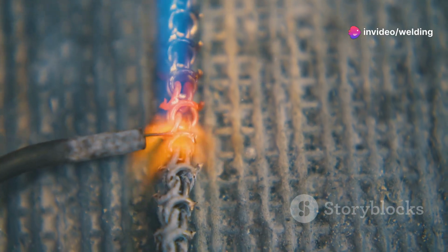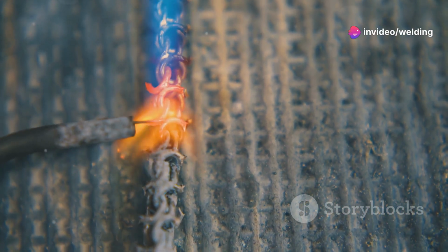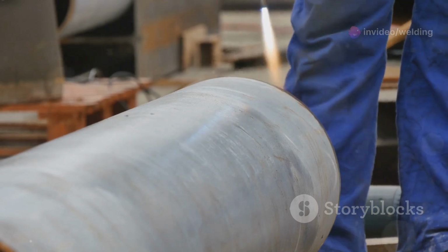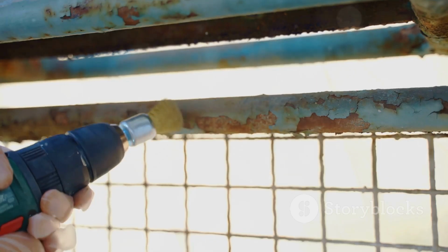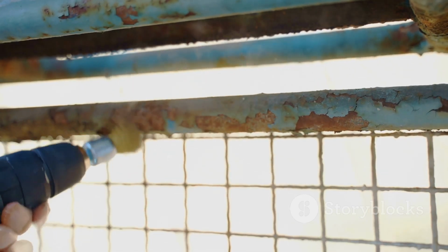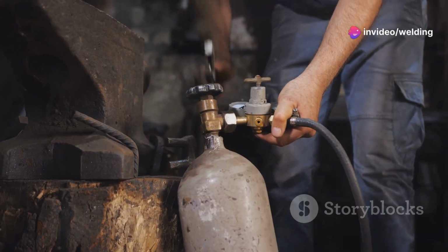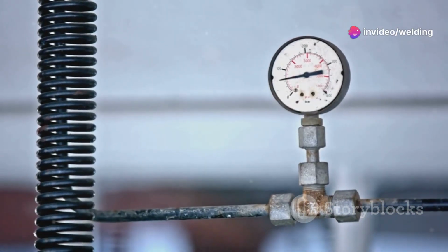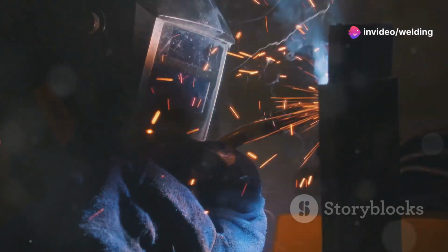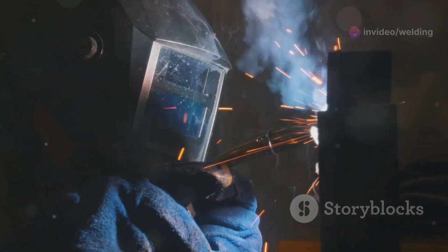Next, let's deal with porosity. Those ugly holes in your weld bead? Yeah, that's porosity. It's usually caused by contamination or a lack of shielding gas. Make sure your workpiece is clean and free from oil, rust, or paint before you start welding. And always check your gas flow rate. It should be between 20 to 25 cubic feet per hour. Adjust as needed to keep those welds smooth and solid.